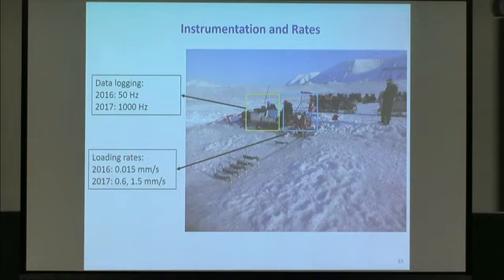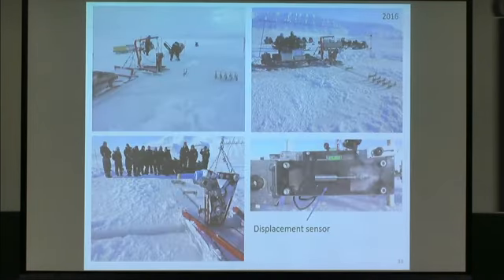What about the instrumentation? Data logging in 2016 was at 50 Hertz, we found that could have been better, so we increased this to 1000 Hertz in 2017. We had loading rates from 0.015 millimeter per second to 0.6 and 1.5 millimeter per second displacement here. And the jack here is in place, lowered down, and it's ready to run one of the first experiments.